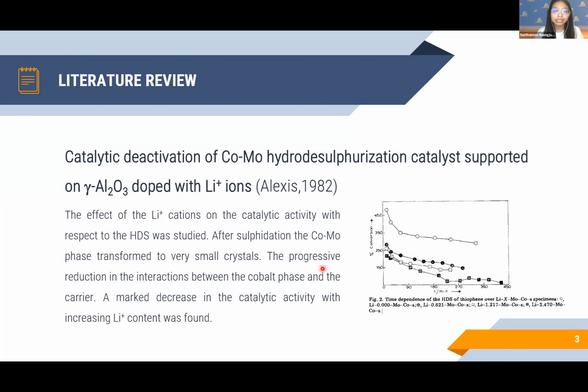Next one is the literature review. First, this research studied the hydrodesulfurization or HDS catalyst on gamma alumina oxide with varying amounts of lithium ion. After sulfidation, the cobalt molybdenum phase transformed to very small crystals, with a progressive reduction in the interaction between the cobalt phase and the carrier. A marked decrease in the catalytic activity with increasing lithium ion content was found.